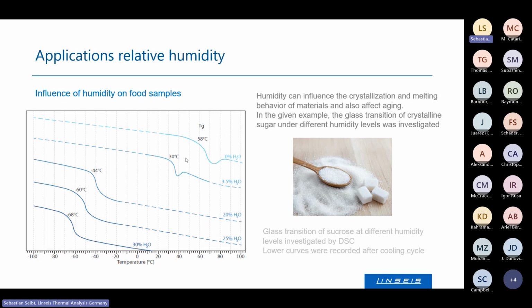What we saw is by increasing level of humidity, the melting point drastically was shifted to lower temperatures. And also by increasing levels of humidity, the glass transition was also shifted to lower temperatures.